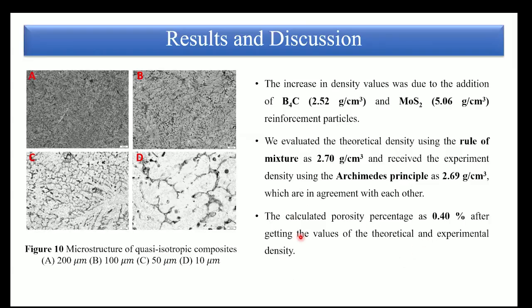Discussion. This is the microstructure of the quasi-isotropic composite at different magnifications. The increase in the density values was due to the addition of B4C and MoS2. We evaluate the theoretical density using the rule of mixture. This is the rule of mixture: volume fraction of metal times density of metal, plus volume fraction of reinforcement times density of reinforcement.